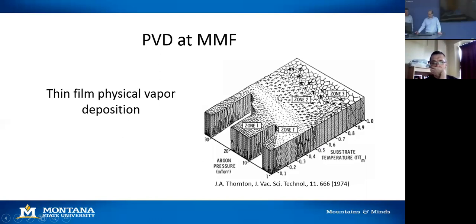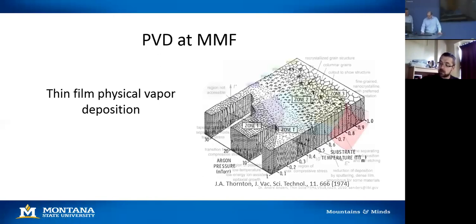And this is specific for sputtering. You have argon pressure on this side. Thing to note, we typically operate in zone 1 to zone T, maybe get into zone 2. But it's very difficult. Depending upon what tool you have, you get limited to where you can deposit, what materials, what kind of morphology you can get.